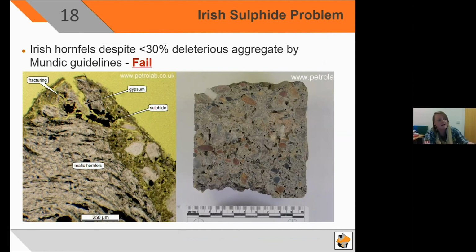And the picture on the right is a core that we did for R&D, which is freeze thaw. You can see that the edges of the core have crumbled off, and at a closer inspection, there is a lot of peripheral fractures that are around some of the hornfels aggregate. So that one actually ended up high risk from freeze thaw.